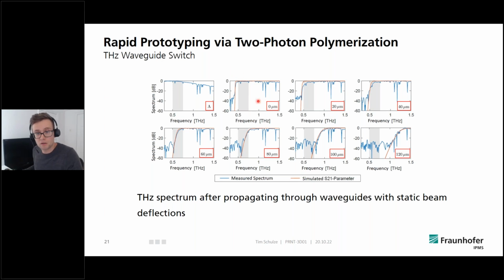I exchanged my printed component with another printed component with a different deflection. So here it's 20, it's 40, and so on till 120. And we see that the cutoff frequency moves on, and still a high degree of overlap between our simulation and our measurement. At the same time, the waveguide is usually only used within the frequency band from 0.5 terahertz to 0.75 terahertz. So when you have a signal within this band, you can also see that it gets attenuated by doing this switching process. And by this parameter sweep, I was able to give a proof of principle of my idea.